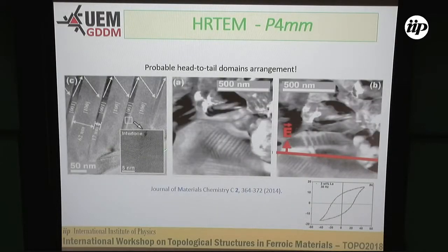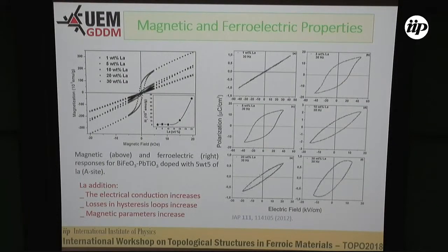And we have this landscape for domains and domain interfaces, and we applied some electric fields, and you see that these domains can be moved, and this hysteresis loop for this ceramic is a macroscopic property that corroborates the microscopic view that we have here. If you change this domain landscape, probably you can change this. And that domain landscape can affect the overall ferroelectric and the magnetic properties.